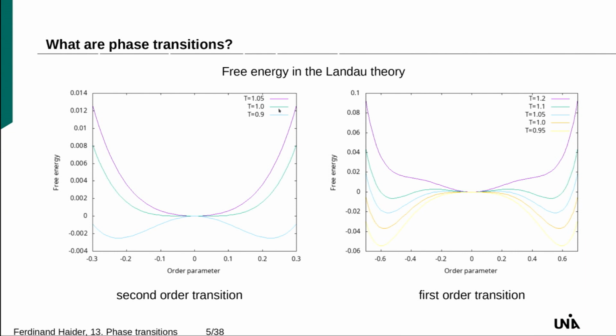At precisely this critical temperature, this parameter alpha changes sign. Above this critical temperature, alpha, which is alpha 0 times T minus Tc, is positive. Below, it's negative. So precisely at the critical temperature, this curve still has a unique minimum here at order parameter 0. As soon as you go below this Tc in temperature, this converts into a maximum, so it changes its curvature here, and two further minima show up. These are just the properties of fourth order polynomials.